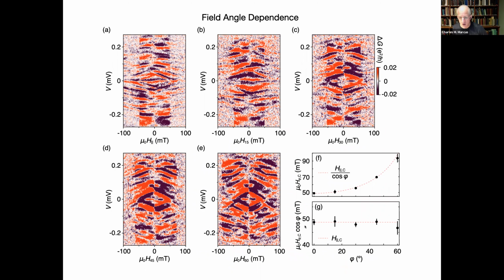How do I know? Well, because if I multiply by the cosine of the angle, that just tells me the amount that's projecting down along the wire, and except for this point, which was a little bit low, it's basically independent of the magnetic field. That tells me that wherever I put the magnetic field, this thing has an easy axis, it's magnetized along the axis, the field is coming out the ends, and it doesn't matter which direction I change it.